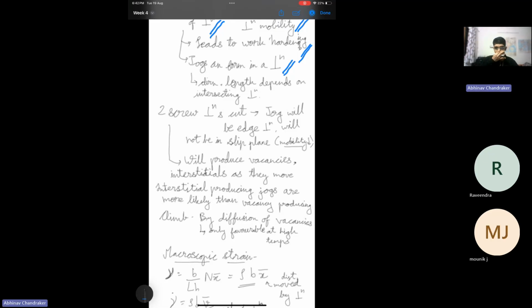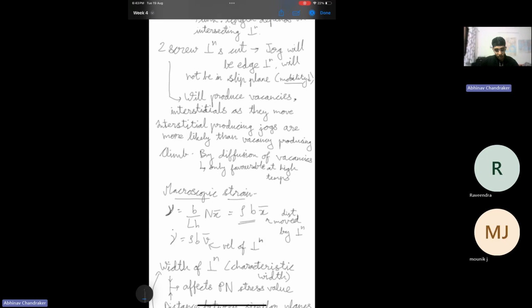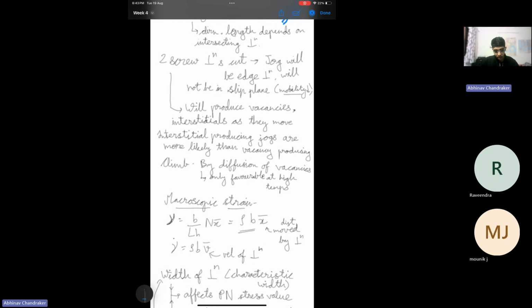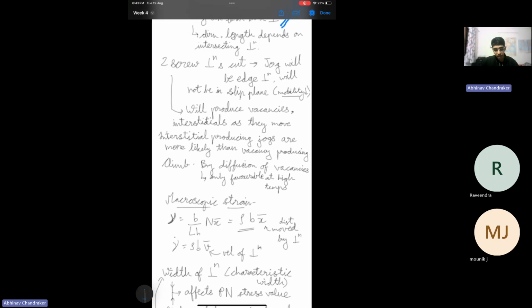So we talked about jogs, how to understand what will be the Burgers vector and line direction of the jog, because that will decide what is the character of the jog. So a jog for a screw dislocation can have edge character and vice versa. The important thing to understand here is that if you have two screw dislocations getting cut, then the jog will be an edge dislocation and it will not be on a slip plane. So in that case, it will be immobile. In other cases, it will be mobile.